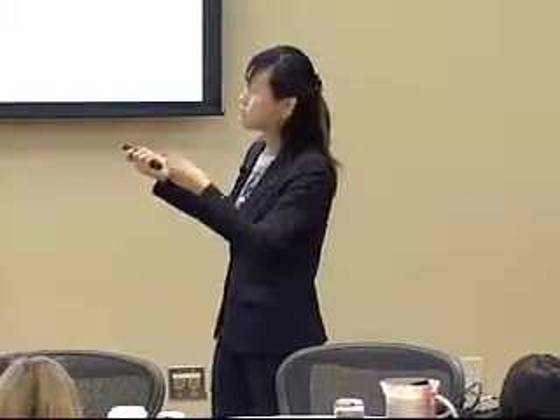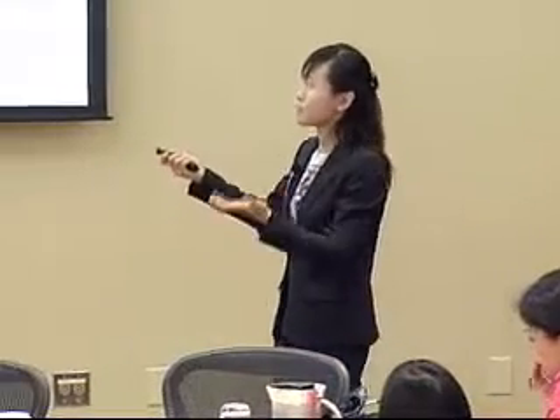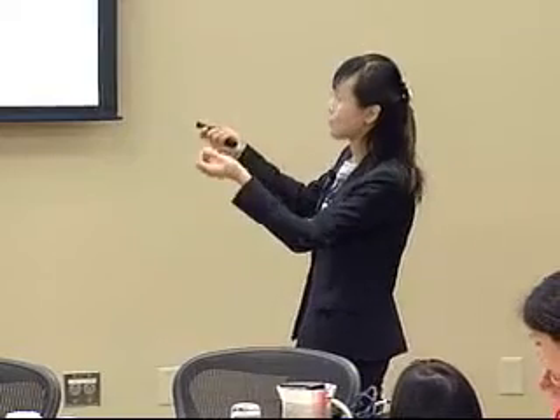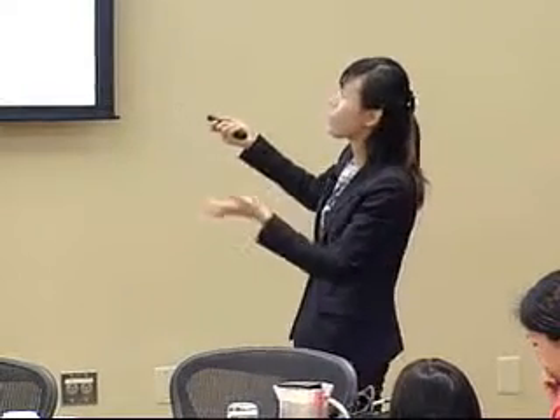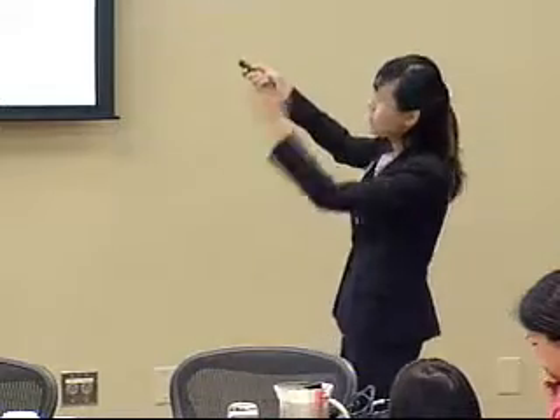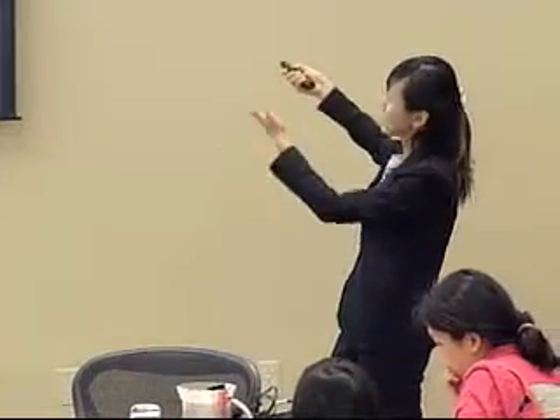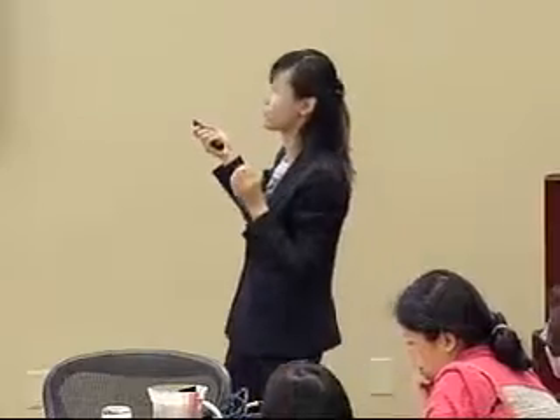Okay, so in terms of silicon islands, people would like to actually use this very stiff Kapton substrate for a lot of printed circuits because it's very robust and easy to handle compared to very soft rubber substrates. So in this case, if we have brittle, fragile ceramic islands, either silicon or silicon nitride, after 0.8% stretch, we see full of channel cracks, and of course it could even have delamination, all those difficulties. But people still like stiff substrate, okay? They don't just like a rubber, very floppy substrate.